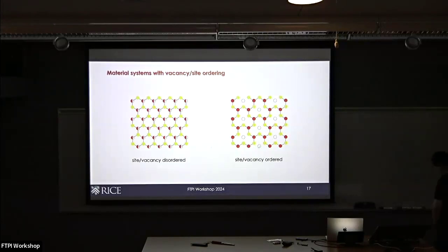So how do you do this? Here is the scenario. One way we can approach this is to consider systems that are not stoichiometric, that have missing sites. You can call this vacancy or site ordering. Here, you can consider two situations. Suppose you have vacancies in the lattice that appear in an ordered fashion. You can imagine there are situations where this could lead to special types of lattices that may fit with this type of topological flat band. And then you can imagine the same number of atoms, but arranged in such a way that the vacancies are random, so you have a globally different symmetry. In this situation, this kind of geometric frustration is actually turned off. So you can imagine that in certain materials there is a vacancy that could order or disorder, and that can give us one of these situations, perhaps a way to turn this topological flattening on and off. That's what we discovered accidentally, but this is at least the central idea behind this.